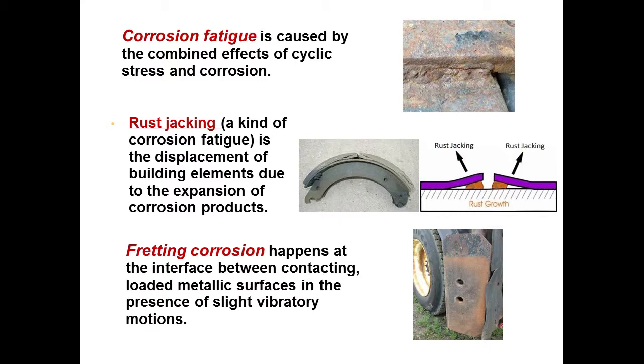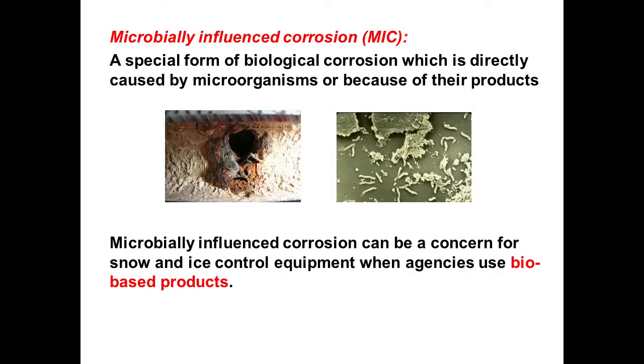And then rust jacking is one type of corrosion fatigue. And also in some cases you have some fretting corrosion, because two pieces of metal are constantly annoying each other mechanically. On top of that, especially when we're using sugar beet or some organic materials as de-icer, we run into this risk even more, which is microbially influenced corrosion. Bugs love sugar. Well, of course, in some cases the desugared molasses is a different story because they no longer contain sugar. But at least they still contain higher contents of carbon and nitrogen, and when the stormwater runoff containing this de-icer gets into adjacent waterways, that's a concern for water quality.